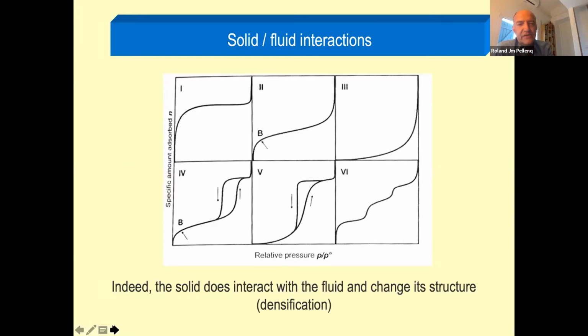Say that we consider curve number 2. This is the curve of an open surface where the fluid actually likes the surface. As you increase the pressure of the fluid, you see adsorption taking place. You have this curve with a B point, and we have a knee forming, right? That corresponds to the building up of a layer at the surface of the pore. So you see that the fluid can be in the gas phase far away from the surface, but it's already in a very condensed phase due to interaction at the pore surface.